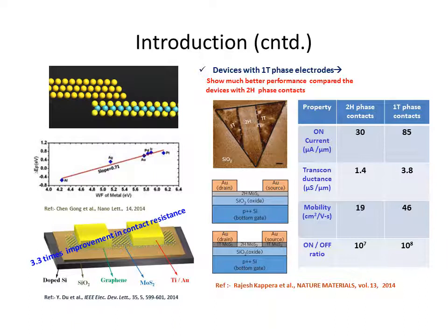Several innovative techniques, like insertion of graphene and TiO2, have also been investigated to mitigate the Schottky barrier limited carrier injection. As I have shown here, this report shows almost 3.3 times improvement in contact resistance and nearly 2.1 times improvement on resistance. But considering large scale fabrication, such a van der Waals heterostructure may not be a suitable choice.